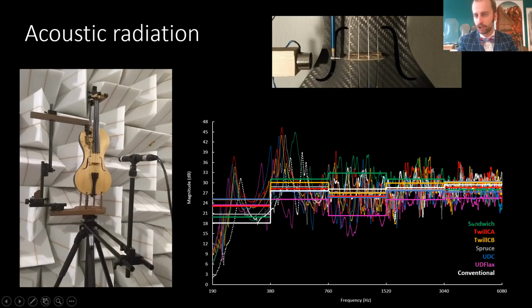Let's look at the extreme examples. The sandwich one was the very lightweight top, 42 grams. And here it has the lowest output of all the violins. But between 380 and 3000 hertz, it has a much higher response than the other violins. Above 3000 hertz it is more or less in the middle again. If we look at the other end of the spectrum, the UD flax violin, unidirectional and heavyweight, here it has a high response, and then it has the lowest response of all of them. So these two are the furthest apart.